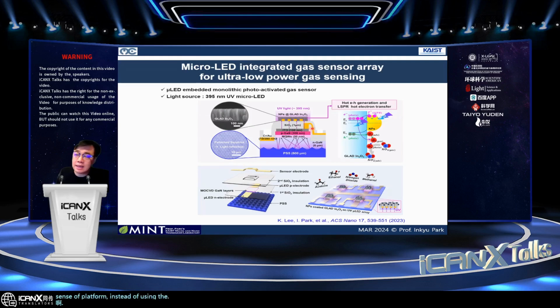Instead of using an external light source, we could integrate the light source with the gas sensor on the same device. So this is the micro LED, gallium nitride based UV micro LED. And then we've got some dielectric layer for the electrical insulation. And you can see the distance between the sensor and the light source is only 1 micrometer, so that you have quite efficient transfer of the light energy directly from the micro LED to the gas sensor.